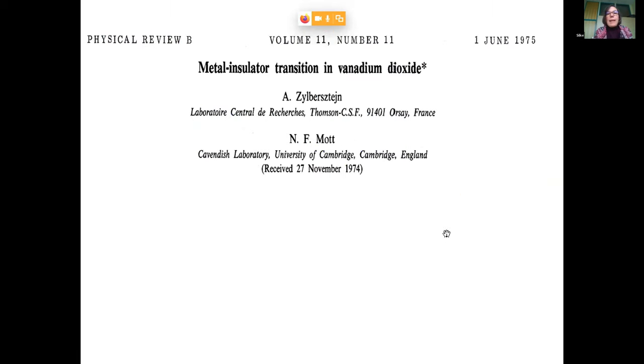Vanadium dioxide has been considered quite early on, and this is a paper by Zylbersztejn and Mott, as one of the materials which is a prototype for a material where yet another effect than electron delocalization in a band structure picture could be important. Namely, this was the famous Mott effect, Mott insulating behavior, where electrons could display insulating behavior because of strong Coulomb interaction effects. So vanadium dioxide was early on proposed in this category.